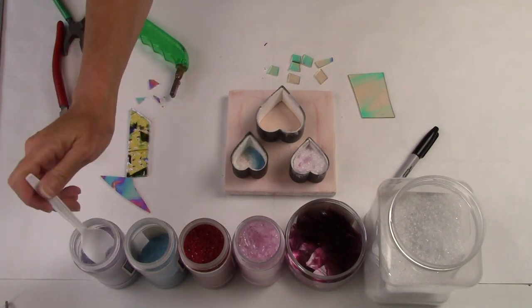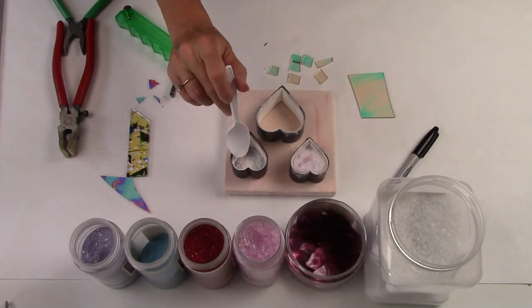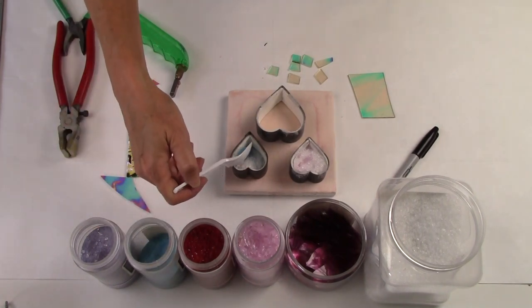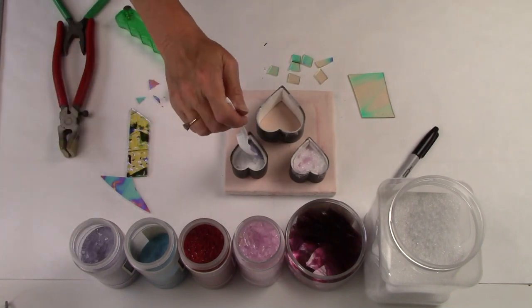In these examples I'm using all transparent colors. Of course you can mix in some opaque if you wanted to. I generally avoid using powder frit when doing cast pieces like this — powder frit causes the pieces to be cloudy. They're not as transparent and they don't have that illusion of depth.